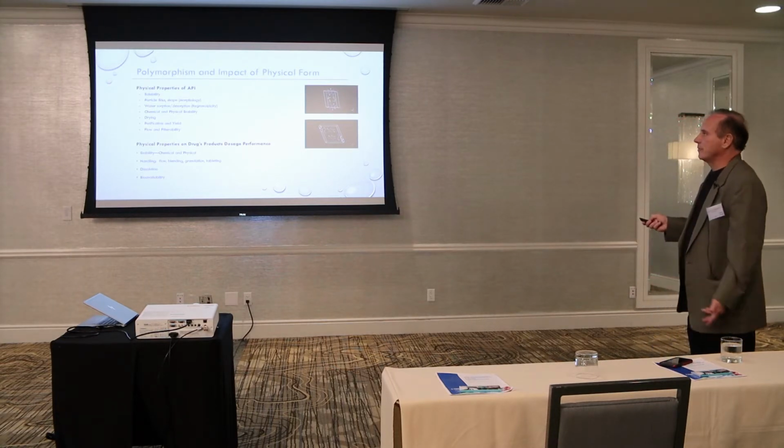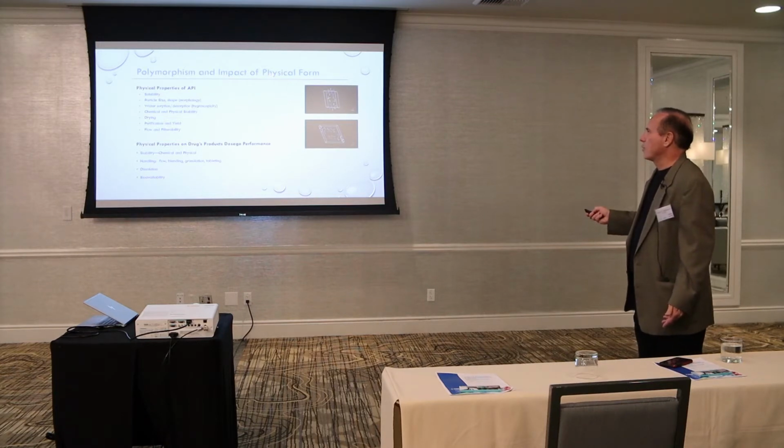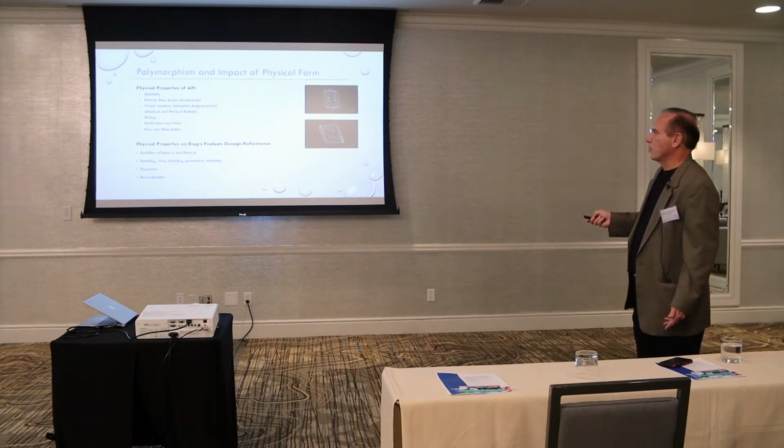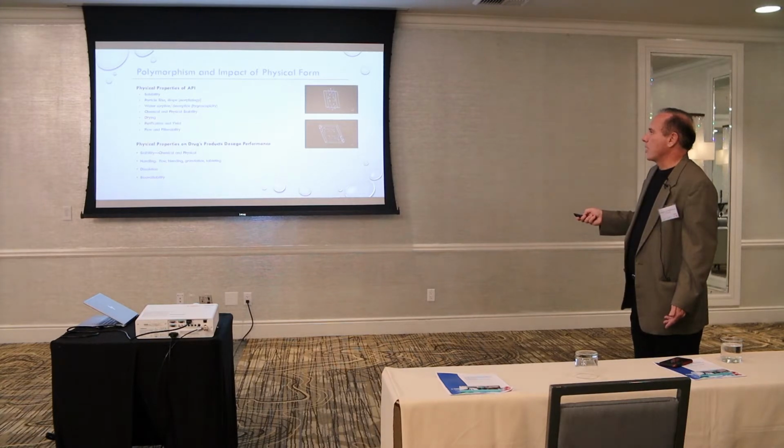And so the physical form has a major impact on physical properties of the active pharmaceutical ingredient, but it can also influence a lot of the product dosage form's performance, many properties in the final dosage form, such things as solubility, particle size, shape, and morphology, water sorption and desorption, or roughly, people call it hygroscopicity, chemical and physical stability, so how much it degrades in the solid state, physically, whether or not it transforms to another solid state form, then the drying properties, purification, and yield, considerable, the actual physical form that you isolate has considerable impact on this. Flow and filterability commonly is impacted by the physical form.